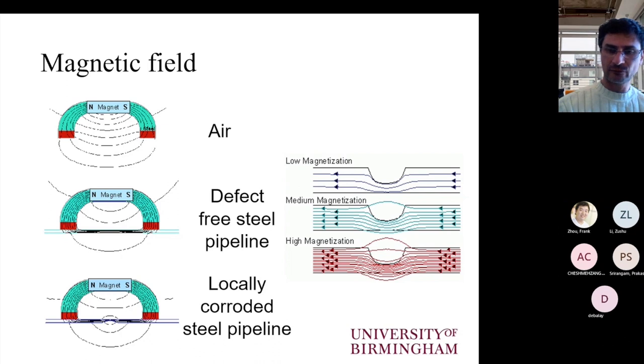The same can be the case when we have medium magnetization. So the leakage may be limited, and that, of course, will lead either to this defect being missed, or it will lead to this defect being underestimated. So it is required that we have sufficient magnetization or high-level magnetization in order to ensure that sufficient magnetic flux is leaking. And of course, that can be related to the actual severity. That is why when we are doing the inspection in the field, we need to calibrate our system for the liftoff that we are operating, because the liftoff will, of course, affect the level of magnetization. So if we haven't done that, that means that we are getting wrong indications, and that can lead to missing defects altogether, or even worse, underestimating defects.